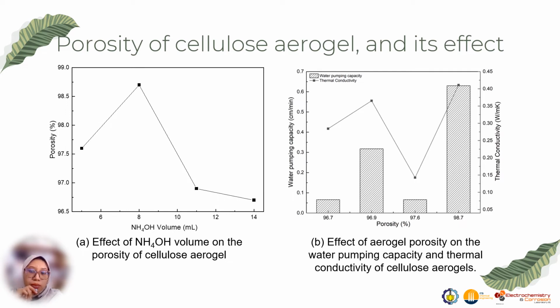As expected, the porosity influenced the properties of cellulose aerogel: water pumping capacity and thermal conductivity. The water pumping capacity increased from approximately 0.06 centimeter per minute at porosity of 96.7% to 0.63 centimeter per minute at porosity of 98.7%. Meanwhile, the thermal conductivity increased from 0.143 watt per meter Kelvin at porosity of 97.6% to 0.4 at a porosity of 98.7%.